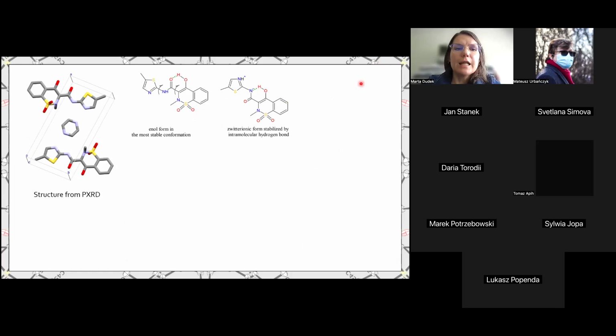Fortunately, we were lucky enough to get a crystal structure from powder X-ray diffraction. This is a solution from powder X-ray diffraction, but there are no hydrogen atoms. But what we saw there is that this is not what we expected. This is an enol form. This is not the Zwitter ionic form, which we assumed is present in the crystal from carbon-13 CPMAS measurements. So this came quite as a puzzle, and we needed to put hydrogen atoms somewhere in this molecule.